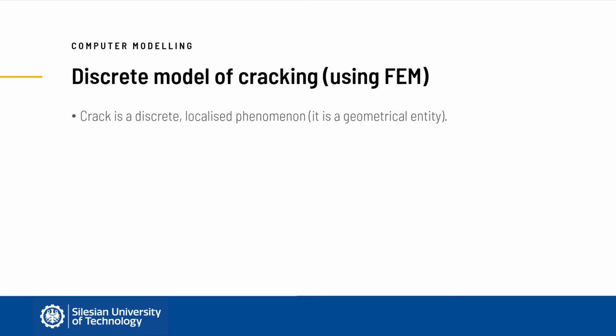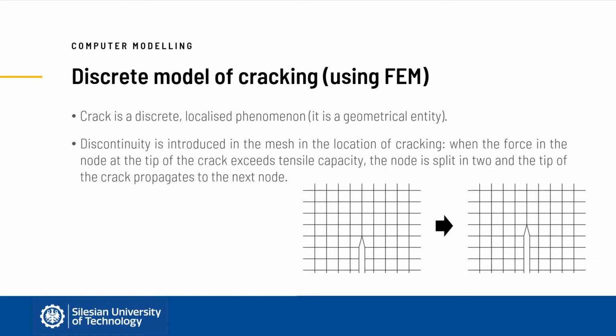In a discrete model of cracking, each crack is modeled directly as a discontinuity of the finite element mesh. When the force in the node at the tip of the crack exceeds tensile capacity, the node is split in two and the tip of the crack propagates to the next node. The advantage of this method is the possibility to determine the exact location of the crack and follow its growth. On the other hand, remeshing must be performed after each step in which a new discontinuity is introduced. This is computationally challenging and hence is rather not used for modeling of whole structures and large structural components.